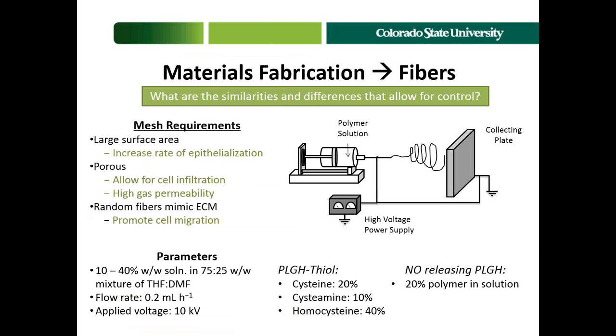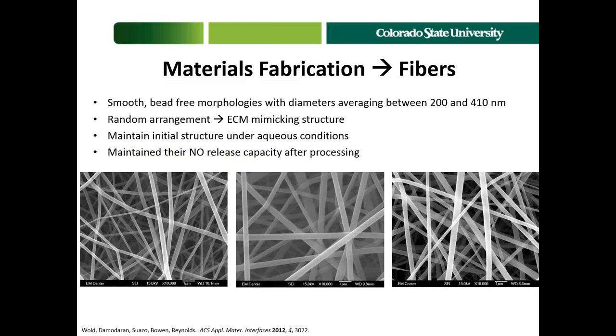We then move and fabricate these materials into forms that actually could be useful. We have tried a lot of times to make nanofibers out of these materials to make mats the cells will be able to have the right porosity to bind to. And we have been able to do this. The materials maintain their nitric oxide release capabilities, and we can get some fine nanostructure properties that mimic the extracellular matrix. These materials also tend to retain their structures, at least initially, in aqueous conditions. In other words, there's a structure in place long enough for cells to actually deposit onto the surface.